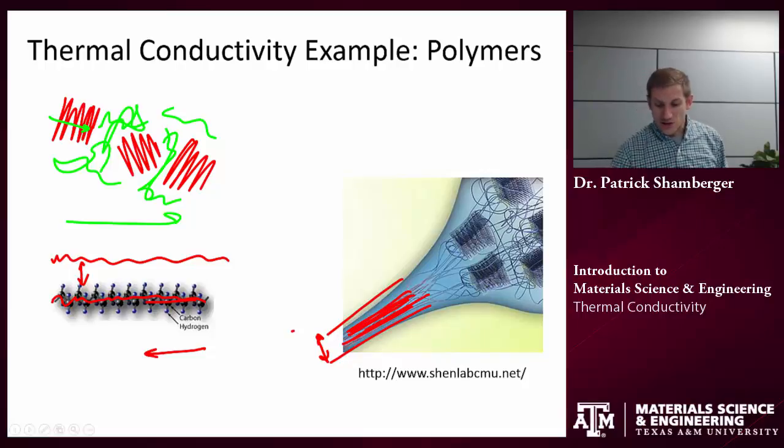So then when they measured their thermal conductivity along the length of the fiber, they got thermal conductivities that were orders of magnitude higher than what we usually see in polymers. So again, the reason why is that we're thinking about thermal conductivity, we're thinking about the two contributions.